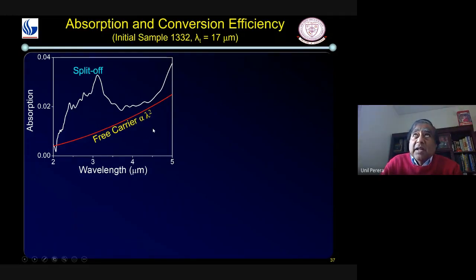We were trying to develop 10 micron those days, but I said, let's measure from 2 micron. This is what we saw. We saw a peak which we were not expecting for free carrier. Earlier we were saying the absorption is due to free carrier, but this is an unexpected result. And it is not free carrier, which goes as lambda squared.